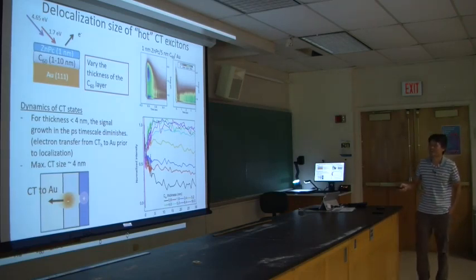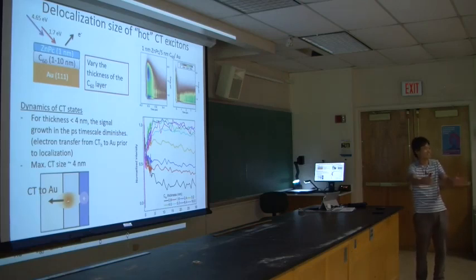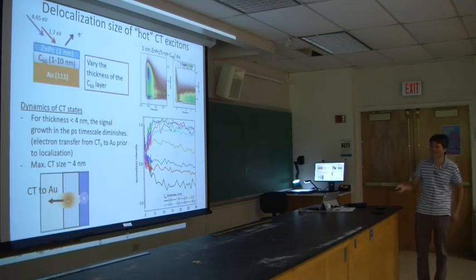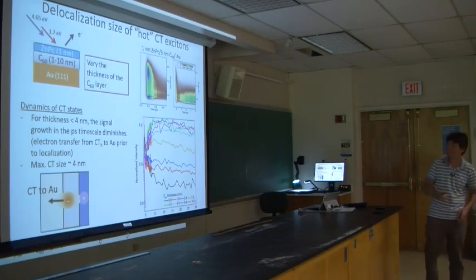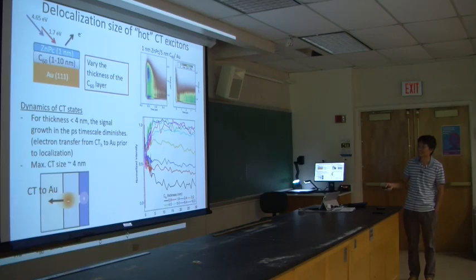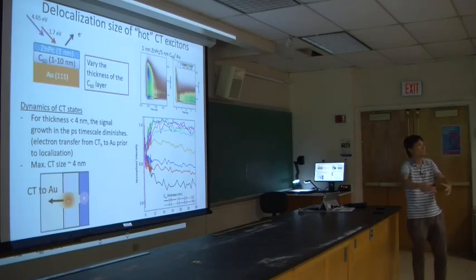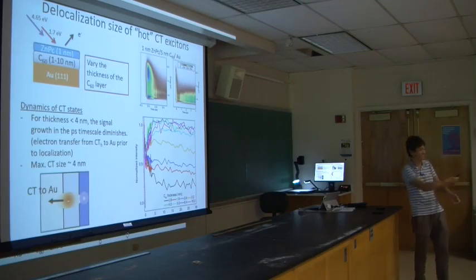Therefore, if your thickness is below the delocalization size of that CT exciton, right? Your electron no longer comes back to the surface. It's basically transferred to gold, and then the whole signal disappears, right? So it's actually what we saw here. For thicker layers, the signal comes back, right? So it rises back. From 10 to 4 is all basically the same kind of dynamics. But as you go thinner, that rise gets weaker and weaker until at this 1 or 2 layer, you basically just see the signal decay, right? So what that means is, below 4, the film is thinner than the delocalization size of that hot CT state. So these electrons got snapped out and transferred to gold, right?